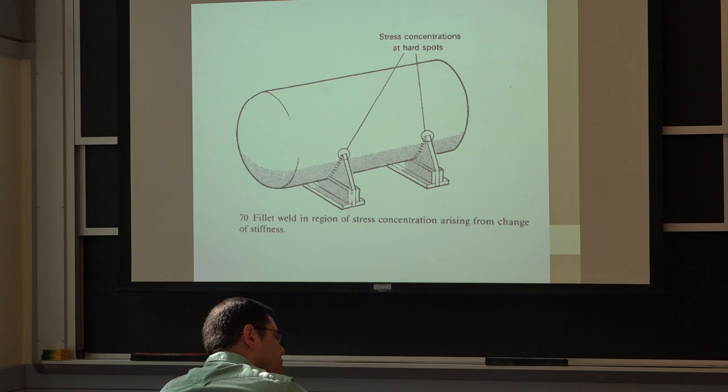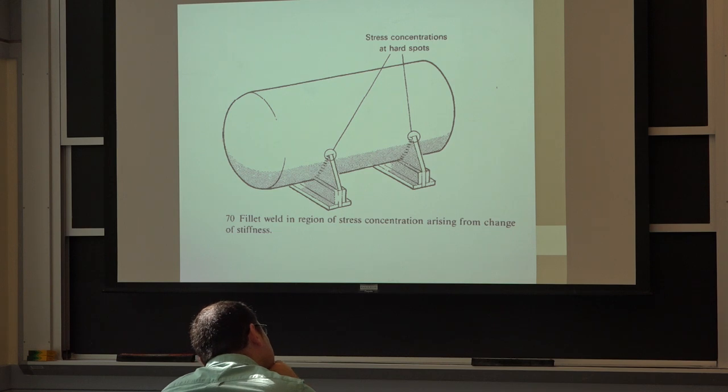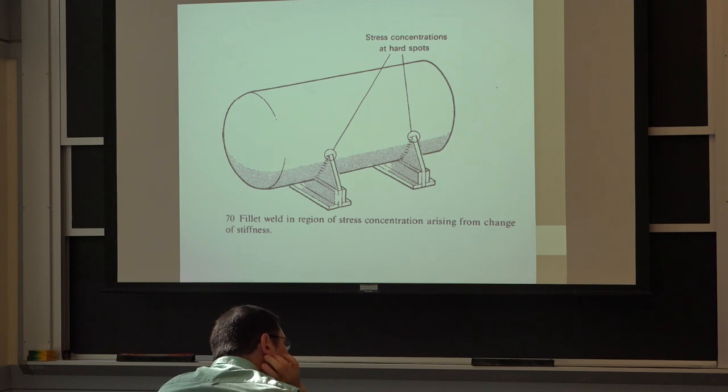If you have a good diffusion bond, you don't necessarily have this. This is when you have a fusion weld, at the corner of the fusion weld, at the toe of the weld. Might as well get another board. If you blow up the corner right here, you're going to find a notch where the liquid hits the solid. You'll see a geometric notch. It may only be 2 or 3 thousandths, okay? If it's a 16th of an inch, we'll call it an undercut and we'll call it a defect. But there's always 2 or 3 thousandths of an inch of undercut.